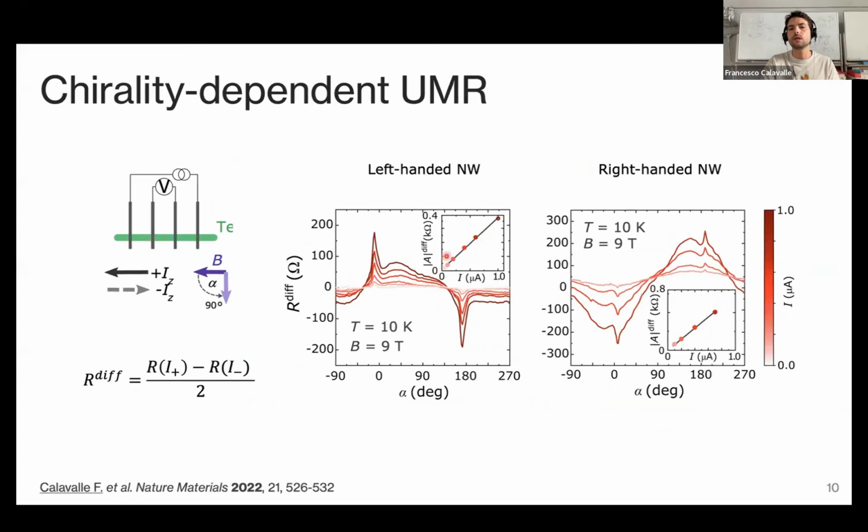So this amplitude of the signal goes linearly with the current applied, which again supports what we suggested as a microscopic mechanism, an Edelstein-like mechanism in which the more current we apply, the more we shift the Fermi circle, and the more we generate a spin density.